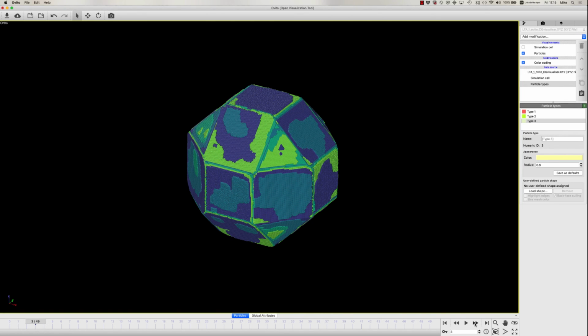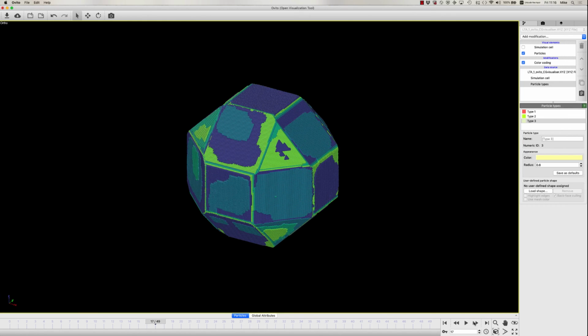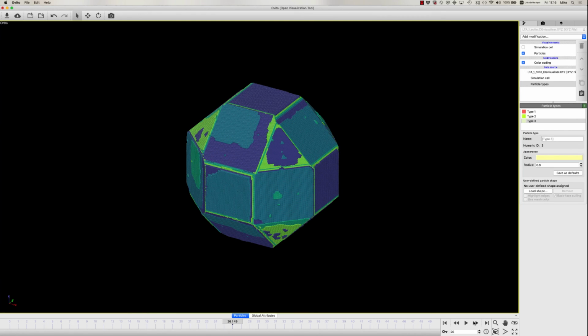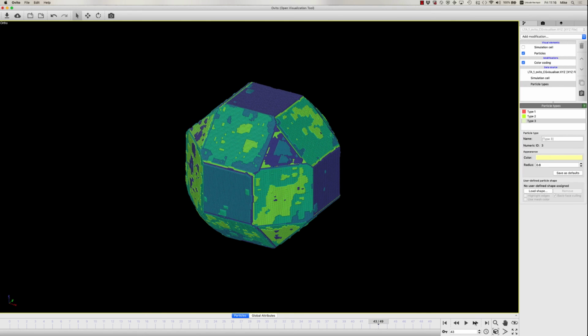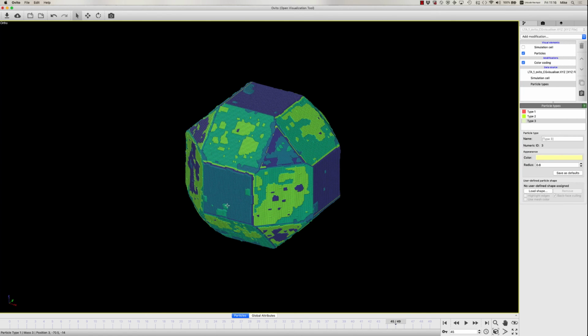So at the beginning you've got nucleation on the 111 facets, that's at 1 kilocalorie per mole. By the time you get to 2 kilocalories per mole, it's really still only on the 111 facets, but by the time you get to 3 kilocalories per mole it begins to take off on the 110 facets now, and then by the time we get to 4 kilocalories per mole at the end, now we begin to see the nucleation on the 100 facets.